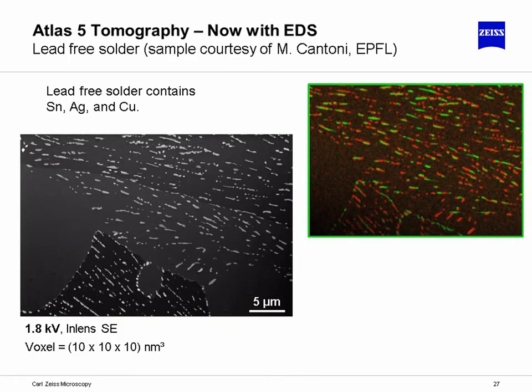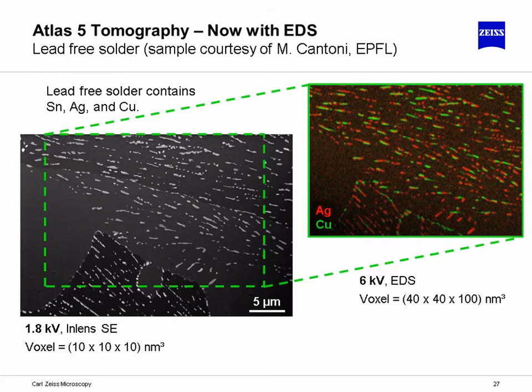In Atlas V, we have recently incorporated the EDS capability. Here is a dataset on lead-free solder, which is courtesy of one of the very first users, Dr. Marco Cantoni from the EPFL in Lausanne, Switzerland. You can see the material contains different precipitates, and now we can add the EDS information to the tomography set.